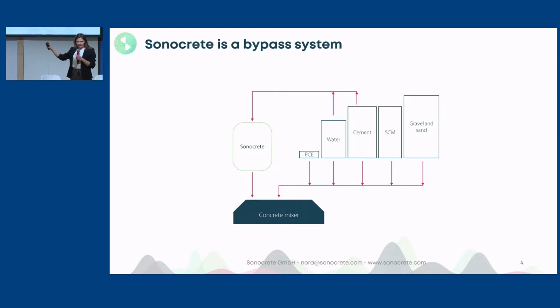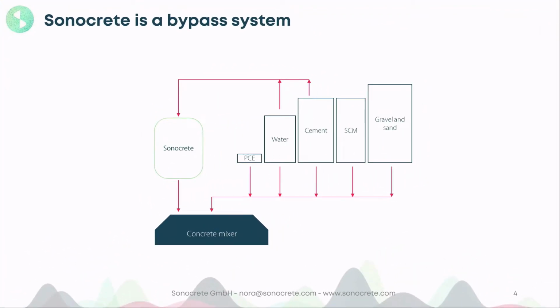When it's time for mixing, this suspension, we call it this activated suspension, is added to the mixer along with all the other ingredients, so the rest of the water, the rest of the cement, and the aggregates. And what the ultrasound does is basically two things. The one is the dispersion effect. The cement is very fine, right? If you make cacao and milk and you just stir it with a spoon, there are clumpy bits in it. And if you use ultrasound, this will just disperse.